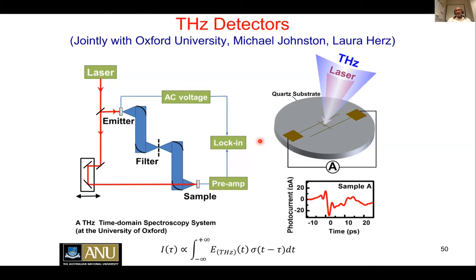So what Kun Pang has done is that she tried to transfer this nanowire onto a quartz substrate, because quartz is transparent to terahertz radiation, and makes electrical contacts using electron beam lithography. And then she shines the light on this nanowire to generate photocarriers, electron-hole pairs, and then comes in with the terahertz pulse. The electric field of the terahertz pulse separates the carriers, and what you measure is the photocurrent as a function of time. As you can see, they are talking about picosecond times. That means it's the terahertz part of the electromagnetic spectrum.